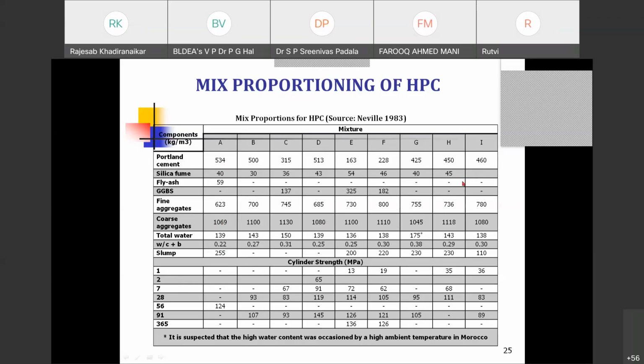Some people are using around 300 to 350 and still producing 100 MPa with increased fly ash content or silica fume content. So you'll find that the main characteristic is the water cement ratio or water binder ratio.